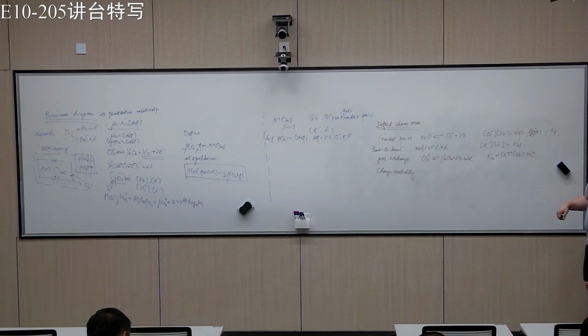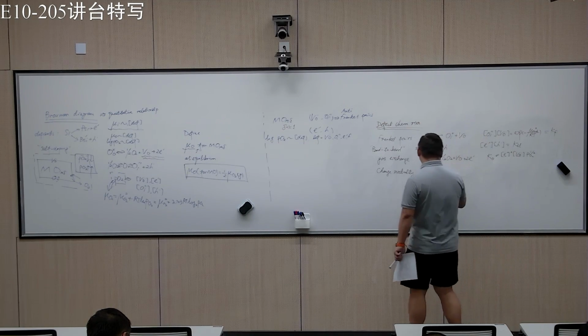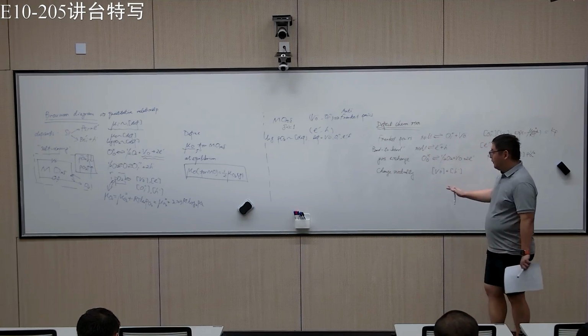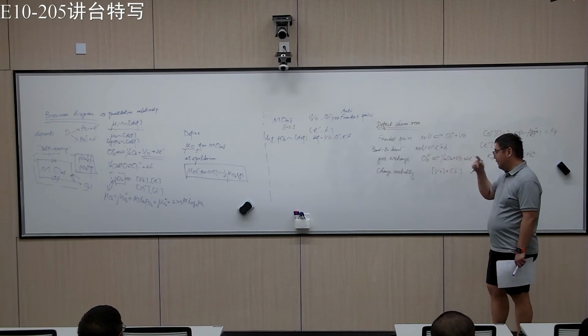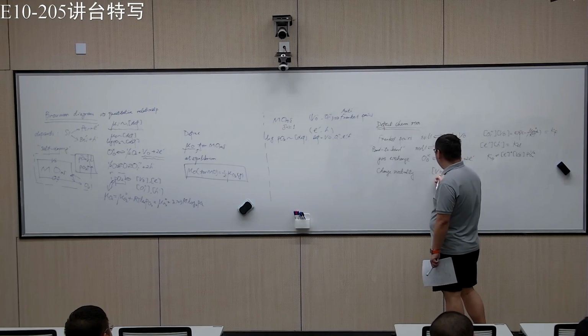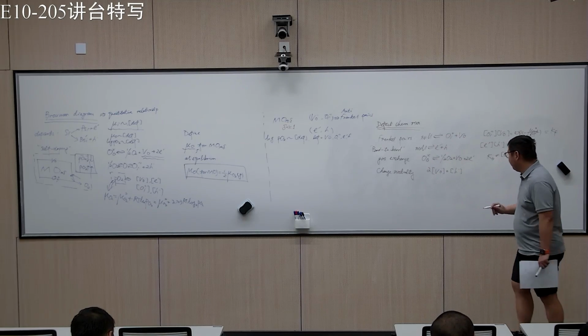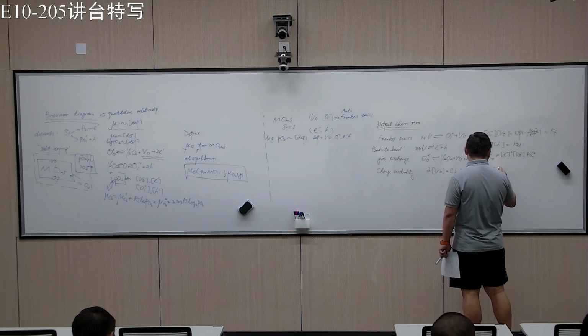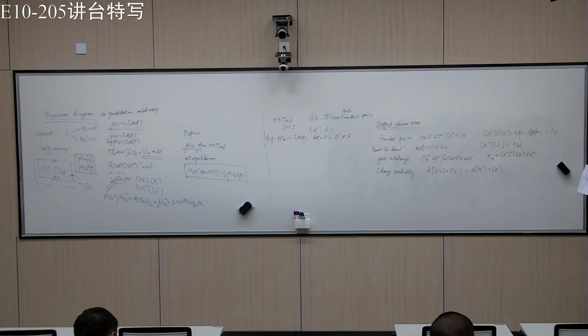So the whole system has to be charge neutral, which means all the positive defects, but pay attention here because the oxygen vacancy has 2 positive charge, right? So when you have 1 of this, you have to put a 2 here. It should be balanced by a negative charge. All right. So we have 4 equations and 4 unknowns. In principle, we should be okay, right?